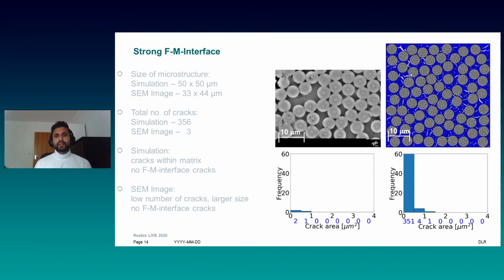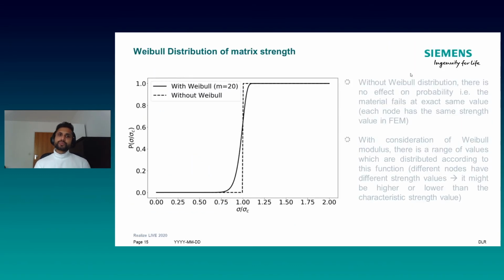The reason behind that is that the volume which we are considering right now is still very small when compared to the carbon bundles which we saw in the SEM images. And even in the analysis, we can see there are 356 small cracks. For this reason, we decided to go to a volume where we have more fibers. And apart from that, we wanted to add one more feature to the properties of the material. In this case, we added a Weibull distribution to our matrix strength.